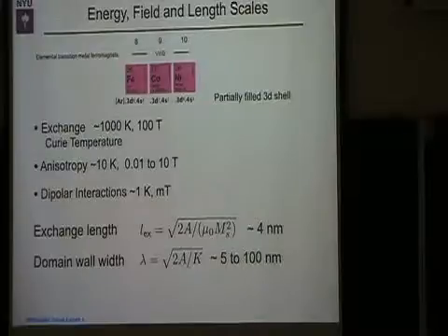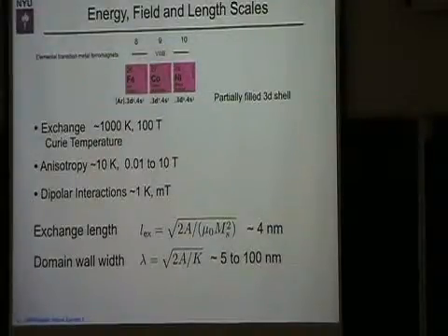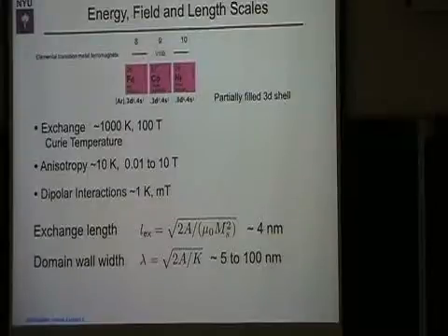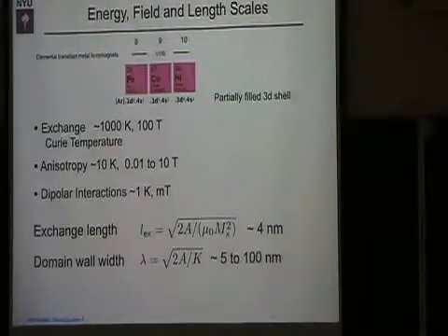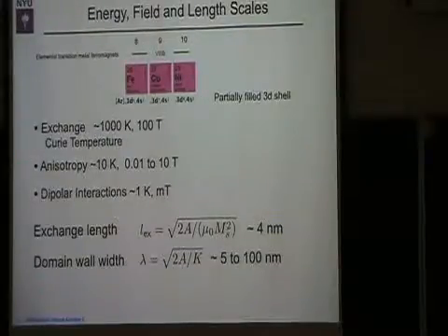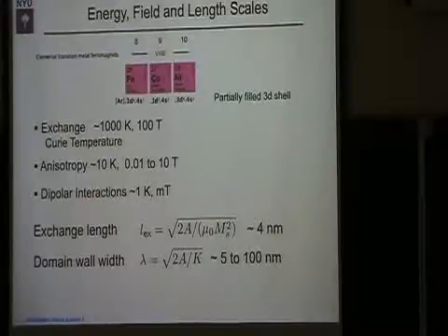So again, I'm going to talk about materials. It's important to know what the length scales are for real materials. If you're an experimentalist or even a technologist, there's a nice simplification in magnetism. There are only 3 ferromagnetic elements in the whole periodic table that are based on the transition metals. I mean, there are some rare earths that are almost ferromagnetic, but the technologically important and high T_C ferromagnets are all based on iron, cobalt, and nickel, and alloys of those materials. And there, the moments are associated with the partially filled d shells of those elements.